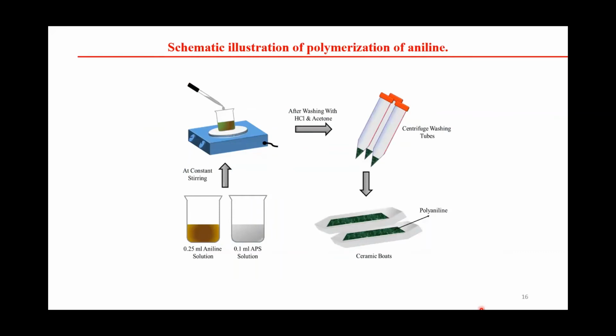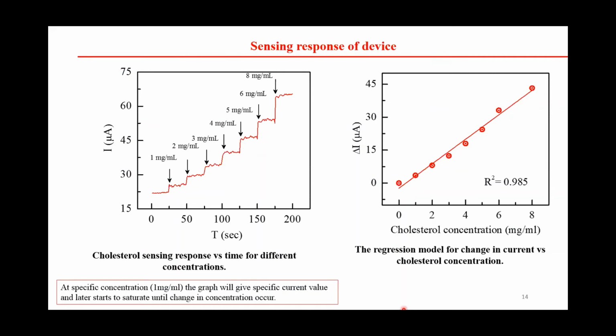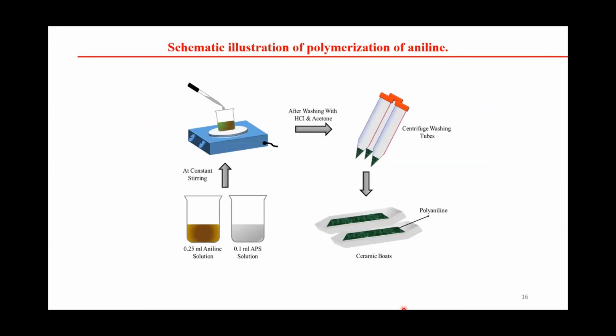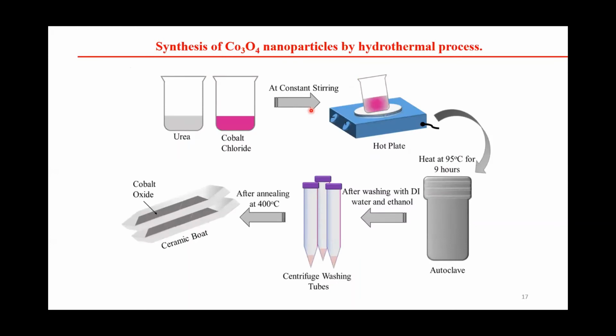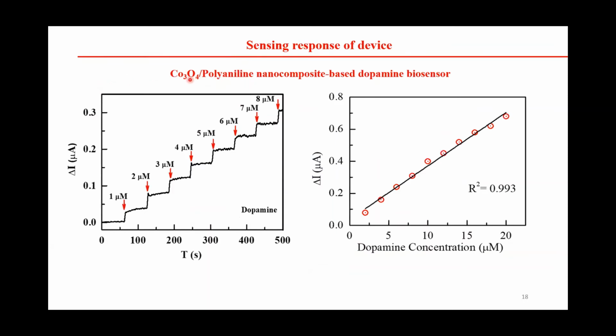There is another device. This process, where we use a bioreceptor before immobilization of our analyte, is known as the enzymatic process. We can also do the non-enzymatic process. In the non-enzymatic process, this is a simple method to prepare some nanomaterials. Here we are preparing cobalt oxide nanoparticles by using a hydrothermal method, and then we use polyaniline, making a composite of the cobalt oxide with polyaniline. Cobalt oxide polyaniline nanocomposites can be used for biosensing.